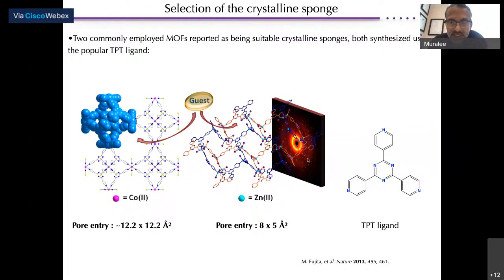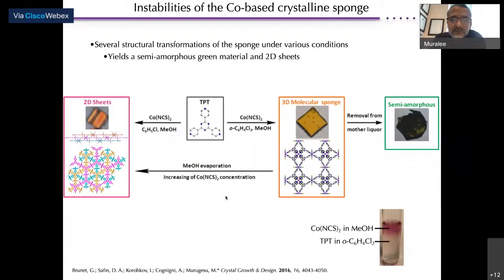So you can do single crystal X-ray, and this is the TPT ligand again used in this MOF made famous by Fujita. There are two different frameworks. Fujita mentions the cobalt and the zinc, they work well, both of them, in this crystalline sponge method. And we wanted to test out if this works for us as well, and if we can do something with it. And when we investigated the cobalt MOF, first of all, there are several structural transformations we discovered.